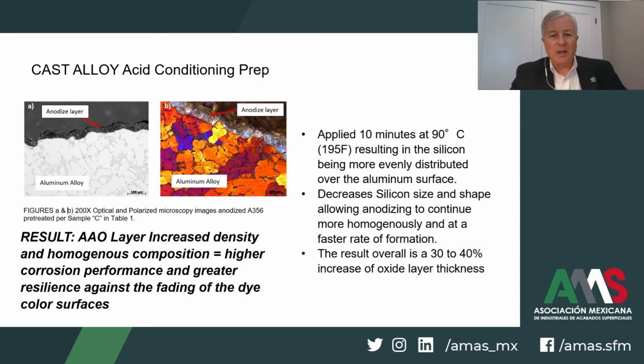The acid conditioning step helps to change the condition of the silicon, and it allows the anodized oxide growth to occur at a 30 to 40% increase in thickness versus not using the acid preparation step. We have developed these new acid treatment activations applied during the processing that helps to manage the silicon in the surface layers by decreasing their size and their shape, and it allows the anodized layer to grow more uniformly, but also without causing the formation of the complex smuts on the surface. So the deoxidizing step is simpler and more straightforward to have success.